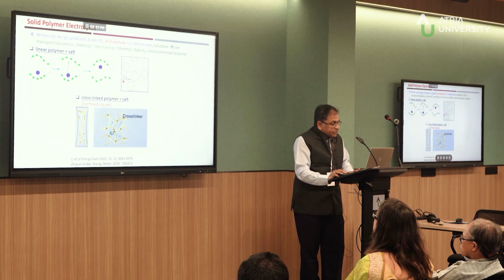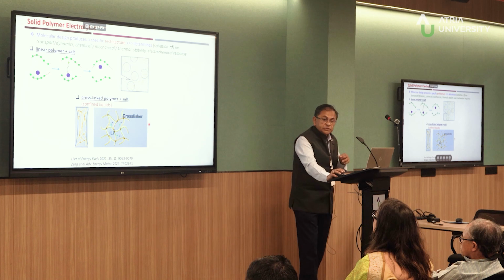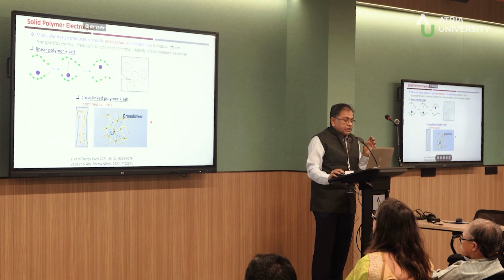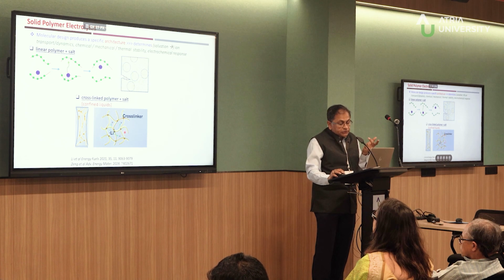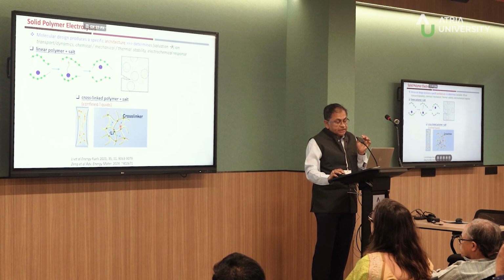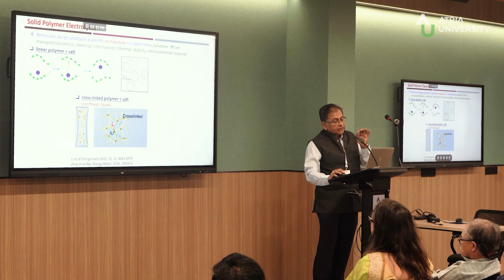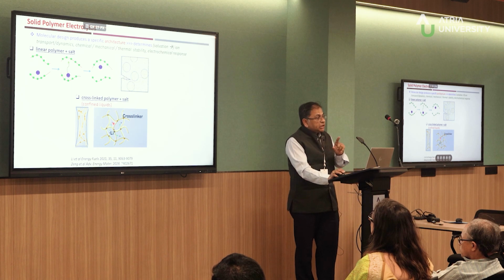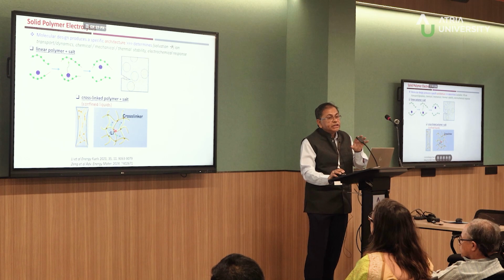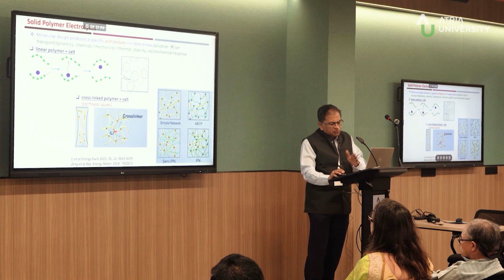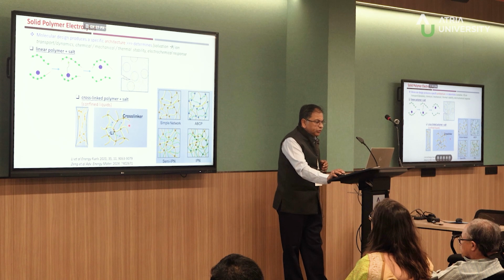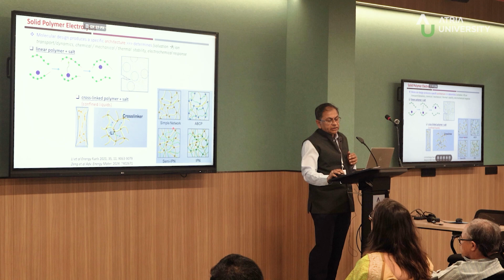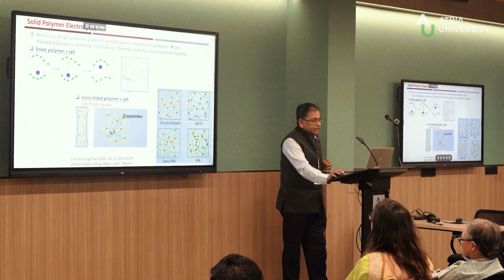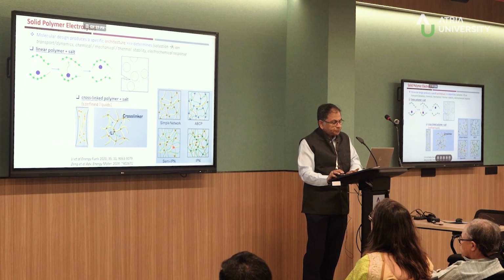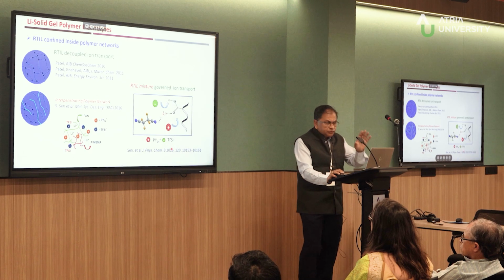So the polymeric systems that we are actually interested in are more cross-linked systems. So you generate these cross-links either chemically or physically, and you have trapped liquids in this empty zone. Okay, so you have the strength of the polymer as well as the mobility of the confined liquid inside the polymer matrix. There are, of course, various versions of it. We mostly stick to somewhere in between a simple network and a semi-interpenetrating network. Alright, so these are some of the earlier designs.